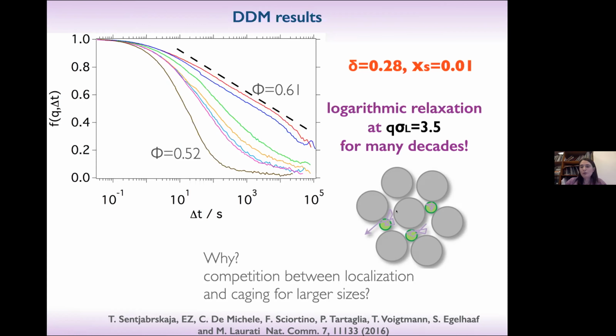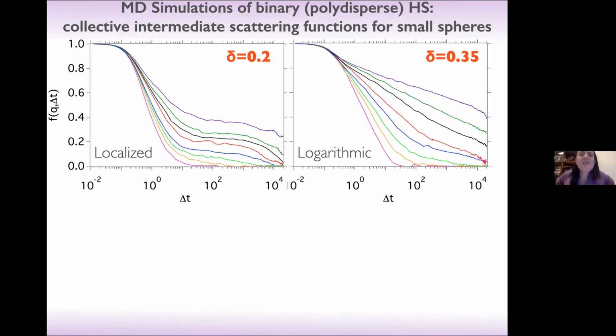So of course, I told you we like to do simulations. So we did simulations, first of all, to see if this could happen. We did molecular dynamics simulation of binary hard spheres, large and small. However, we also had to use a binary polydisperse mixture, because otherwise the large hard spheres were almost one component, because the small ones were very few, and they would crystallize.